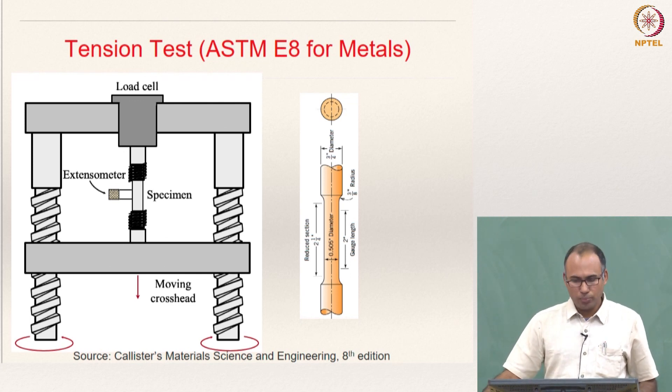We also use something called an extensometer — in other words, a strain gauge — to actually measure deformation precisely. Many times people use crosshead movement as the deformation, but that is not going to be precise because there are losses from frictional interaction between the crosshead and screws, machine stiffness, and slip in the grips. To avoid these errors, you use a strain gauge extensometer connected between two points in the gauge section of the specimen.